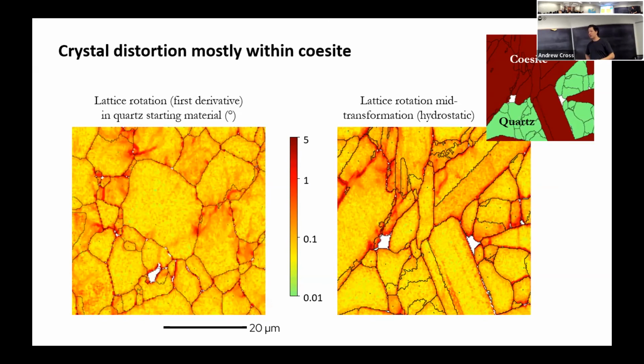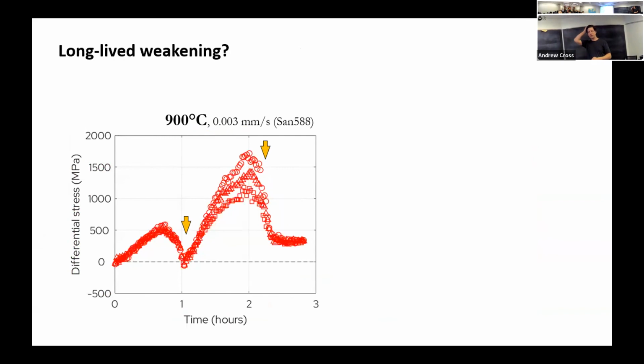So the quartz is undeformed, but if we now look at the coesite, this is again where we're picking out all of our defects and all of our hot colors corresponding to local bending and deformation of the lattice. So the same thing holds up. It's not the quartz, it's not the original phase that's being replaced that's deforming, which is what a lot of the theory would suggest. It's actually, we're getting a lot of deformation in the new phase, the thing that's new phasing. So we're still trying to figure out what that all means and how that scales as a function of temperature and stress and strain rate, stuff like that.